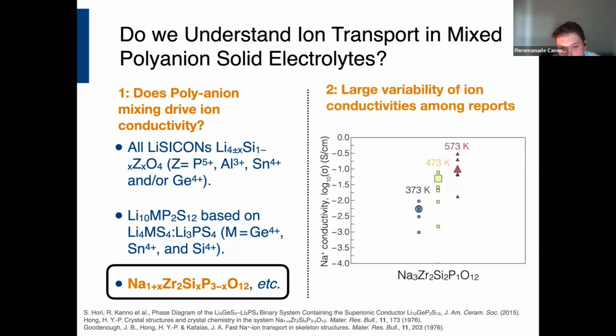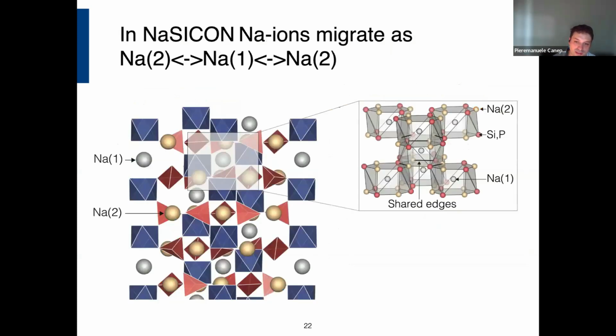The second aspect that maybe some of you are interested in is that there is a large variability in reported ionic conductivities. And here we are talking about ionic conductivities that have been reported over many years at different temperatures for this NASICON composition, where the sodium content is fixed at x equal 2 or 3. You can see that given a composition and a temperature at which the measurement was reported, there is a large, significant variability of the conductivity that is reported. So I will try to show you that maybe computation, or theory, can be helpful in that sense.